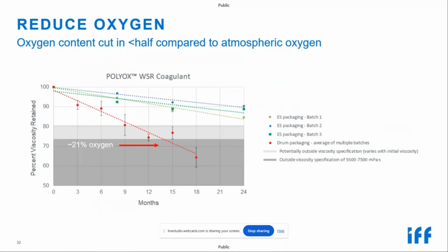Another way that we're finding that we can slow down the viscosity loss rate, slow down that auto oxidation rate, is through reducing the oxygen exposure to the powder. In this study, we cut the oxygen content within the package to less than half of the atmospheric oxygen. So atmosphere's oxygen is about 21%. We were able to get less than even half of that through using a new package type that allows for very, very slow oxygen migration through the packaging. Our current packaging using fiber drums has no oxygen control associated with it. We will offer this package type, this extended stability packaging, next year. So look for that next year.